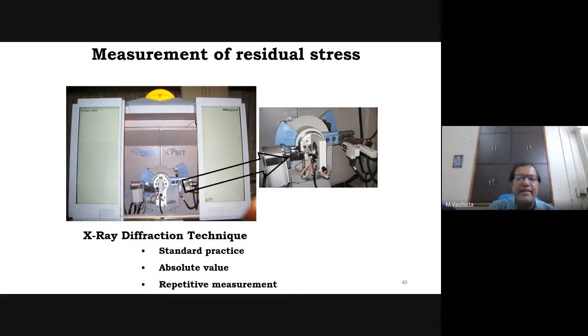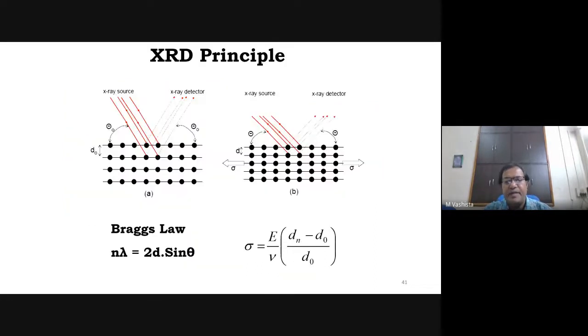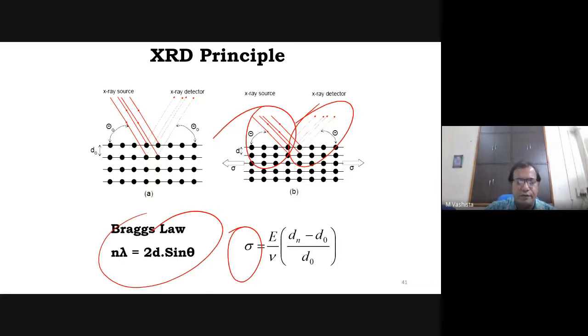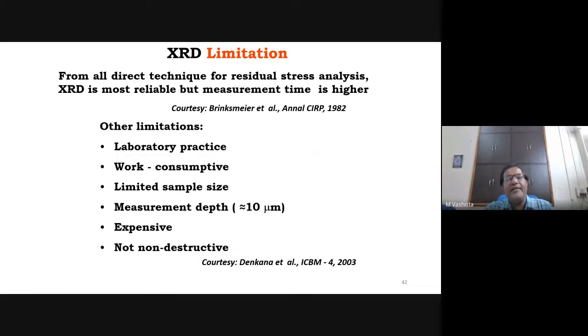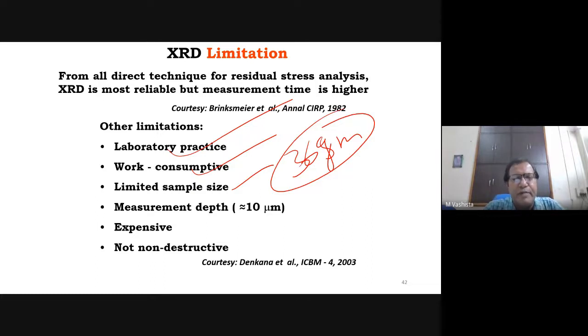This is the X-ray diffraction technique. X-ray diffraction is a standard practice for assessment of residual stress, but in this case we use X-rays, and by using X-rays and Bragg's law we can find out the magnitude of residual stress. But this technique is not eco-friendly, and this is a laboratory based technique. It takes a lot of time. 56 minutes is typically required to scan a sample in an X-ray diffraction machine. Sample size is limited. Typically a 35 gram sample is to be mounted, on the holder of the machine. The measurement depth is less. The technique is expensive. 1 crore rupees is the equipment cost, and this technique is not non-destructive in nature.